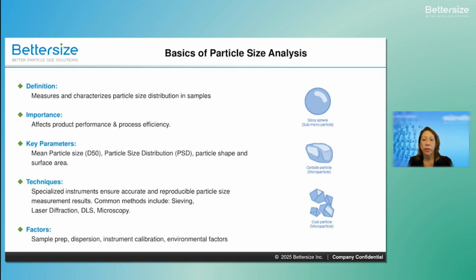Dynamic light scattering analyzes particles by measuring fluctuations in scattered light to determine size, and this is best for particles in the nanometer size range. Microscopy allows for direct visualization and measurement of particle size and morphology in samples from less than a micron up to 25 millimeters. However, no single technique gives the full picture, and often a combination is used.